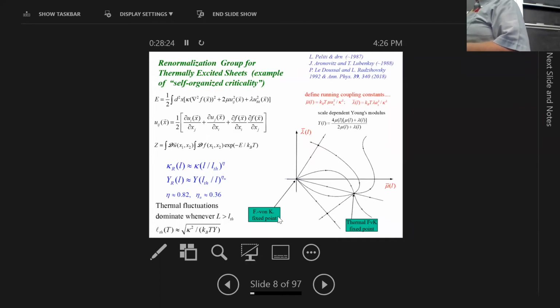It's quite big. And then the Young's modulus, which tells me how easy it is to pull on this thing. I have stored length in the form of wrinkles. It gets softer. And it gets softer in a scale-dependent way. So none of these elastic constants are actually constant. They depend on the size of the system, even though 300 years of science suggests that they are constant at long wavelengths. It's not true for this particular system. And the Young's modulus gets softer and softer.